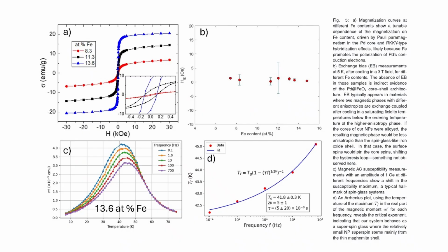Now let's look at the magnetic characterization. First, the magnetization curves show that the saturation magnetization depends on the iron content. This can be explained by the combination of paramagnetism from the palladium core and Ruderman-Kittel-type hybridization effects, where iron promotes the polarization of palladium conduction electrons.